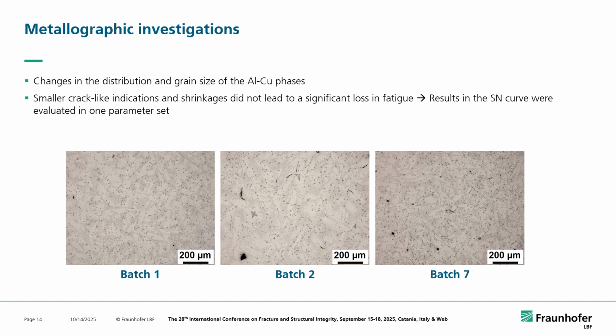And so we could evaluate this S-N curve in one parameter set. And if you remember, the scatter bands going up to 1 to 1.2 or something, this is really in the specification of a typical cast material, so there's nothing to worry about in this case, we would say. So as a result, we will look a bit deeper into that in the next month to get some more information, and also more information about the influence of those iron phases, giving us those signs on the surface after the pre-corrosion.